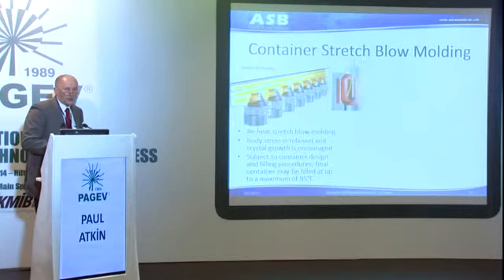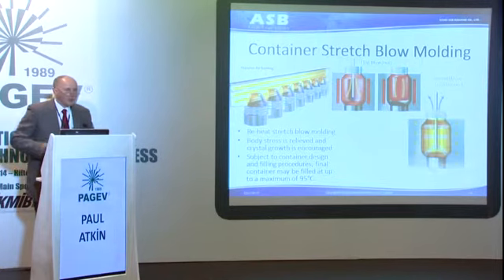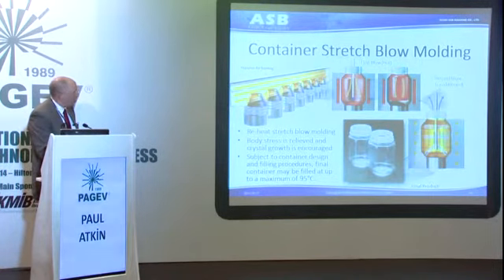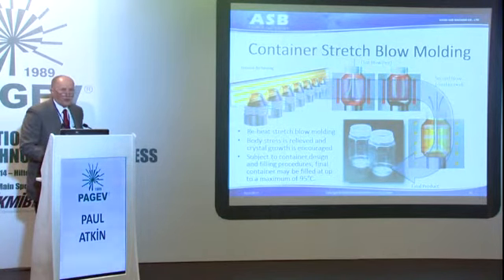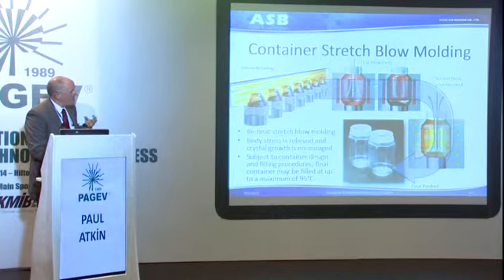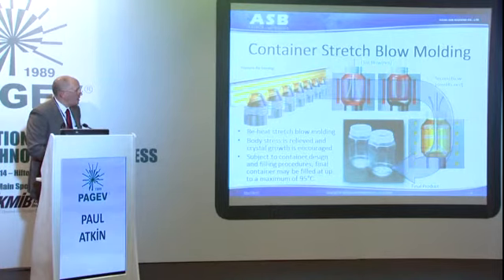Now, once we have the preform, we pass it to the blowing machine where we provide normal reheating, and then we blow the preform into a very hot blow mold. This is around 180 degrees C. So we inflate the preform, and then we release the air, and immediately this container is going to start shrinking, but also crystals are growing in the material. We then pass it to the final blow mold where the final shape is made, and this is also running hot, around 95 degrees C. And the final result is the container is produced with low stress, good clarity, and up to 95 degrees C heat resistance.